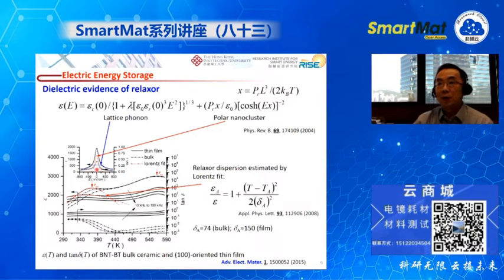And we also measure the dielectric constant as a function of the external electric field. And the obtained result can also be simulated by this formula. The first term in this formula means the lattice phonon contribution. And the second one, which is indicated by this red curve, is caused by the polar nano clusters. And from the simulation, we can find this dielectric constant has a larger component of this contribution from the polar nano clusters. So this is another evidence that the film consists of a lot of polar nano regions, which is a feature of the relaxor ferroelectrics and antiferroelectrics.